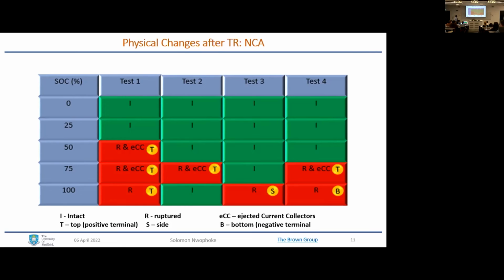You can see from here that up to 25% state of charge, none of the NCA batteries ruptured. Then from 50, some of the batteries ruptured, but not in a very regular order, because at some states of charge you see some rupturing and ejecting current collectors, while others stayed intact. As we move further, for 75 and 100, the same happened. So it didn't show a very regular order. But all I can say here is that from 50, the battery could rupture and release content. There's a probability that it happens, and a probability that it doesn't.